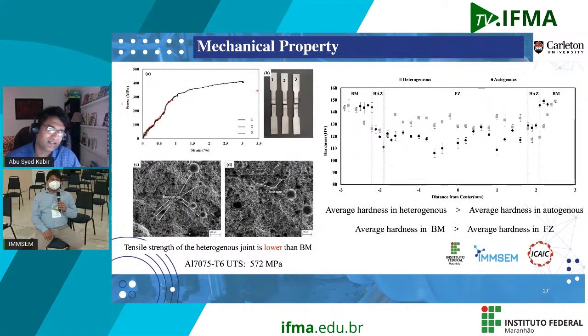So the reason for these changes in the mechanical properties, as I mentioned before, is that we used high heat input that created a lot of porosities in the fusion zone, and the fusion zone was the reason why we have such a low mechanical property.